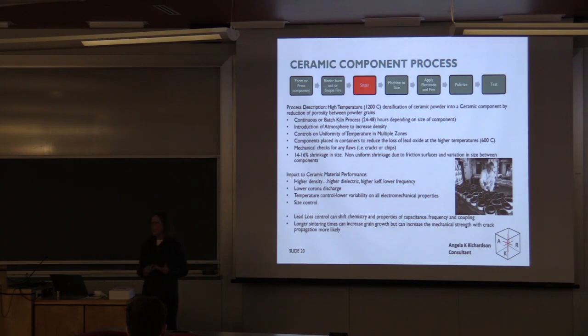And when you have a specification you have to reach at the end, you could have a lot of waste. And so your yield can be very poor. So it's so critical that you're maintaining a uniform temperature there. And we're talking about 2 to 5 degrees Celsius within that scope of distance. You can add atmosphere. In the piezo world, we typically might add oxygen as an atmosphere to increase the densification. The components themselves are placed in saggars, typically alumina crucibles, to contain the lead volatilization.